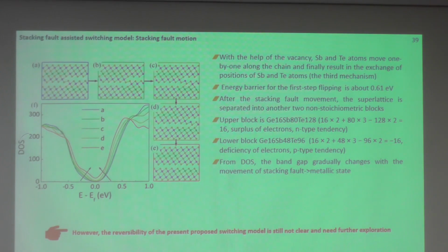So we know that the stacking fault, the bilayer stacking fault, is the change of the height of building blocks from one side to the other side. So here we have antimony units close to the van der Waals gap, like that, here also. And now if we allow this bilayer stacking fault to move to the right, here we flip the atoms to the van der Waals gap.